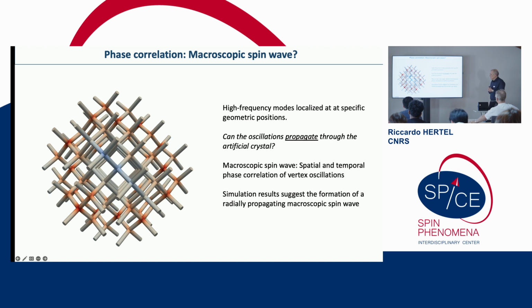What we were looking for, or what we thought we would have found, I must be prudent in the statement, is some kind of macroscopic spin wave. We thought it would be nice to generate something which could be a magnetic metamaterial where the dynamic properties are determined by the geometric features of this crystal, so that you can maybe host spin waves whose frequency and wavelength is correlated in some sense with the geometric size of these bars and not to the magnetic material itself.